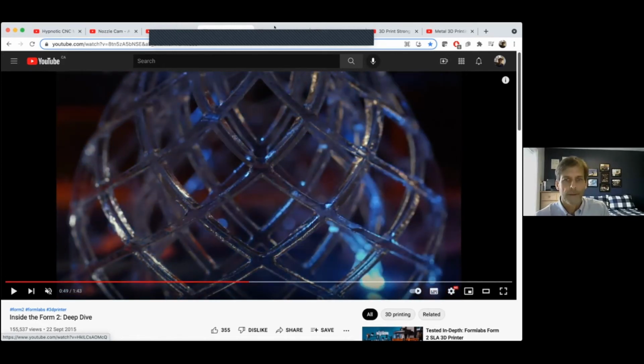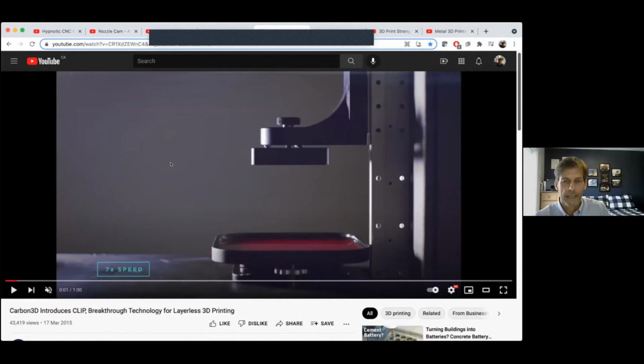A very clever modification of this process has happened in the last, I think, 5 years, and that's by a company called Carbon 3D. And let me explain how this works. This is the same inverted stereolithography. That platform is going to descend into the bath of resin, and in this case, I think it's a digital light projector, so they print the whole image at once as opposed to a single laser beam. But they've done something incredibly clever, which is that the bottom of this tray is porous to oxygen.